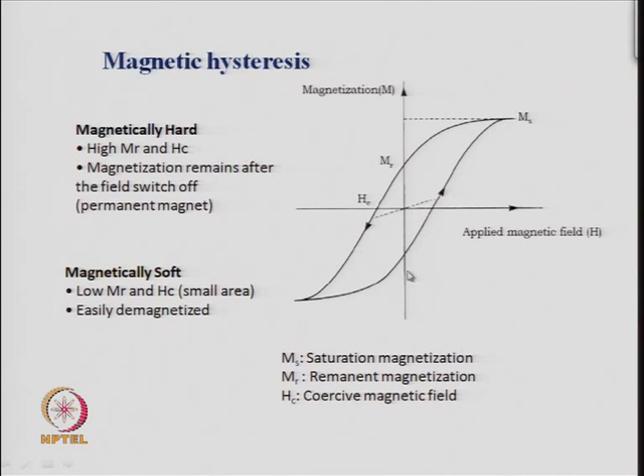So, it goes in the negative direction and reaches a saturation which will be equivalent to the saturation magnetization in the opposite direction. So, here whatever will be the value, you get a negative value, that means a magnetization in the opposite direction with a similar magnitude. And then if you again retrace the path, you increase the magnetic field, you will again see an increase in the magnetization. So, this particular loop of magnetization as a function of magnetic field is called a hysteresis loop and is typical for ferromagnetic or ferrimagnetic systems.